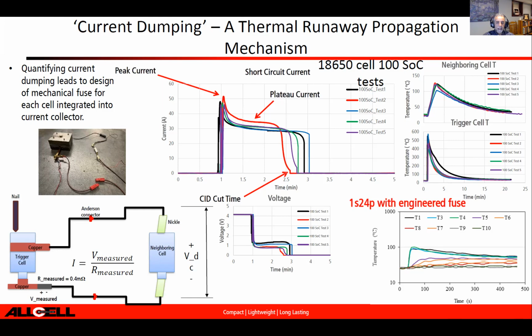The reason this is critical because if you don't stop that, you're going to end up with cells temperature exceeding hundreds of degrees and causing major problem across the pack on top of the thermal runaway cell that adds thermal energy. And what we've designed, we have designed what's called fusing. Most companies, battery companies, have a lot of work into that. They have different fusing techniques. And in our case, we designed fusing on both ends of the cells. This is proprietary. This is something that we work on carefully with our suppliers and cell suppliers and our customers. And what you've seen here, when you fuse the cell, that even when a cell failed catastrophically, the other cells heat up, but they don't go into thermal runaway and they don't exceed because the current dumping has been eliminated, and once the cell is isolated from the rest of the pack.